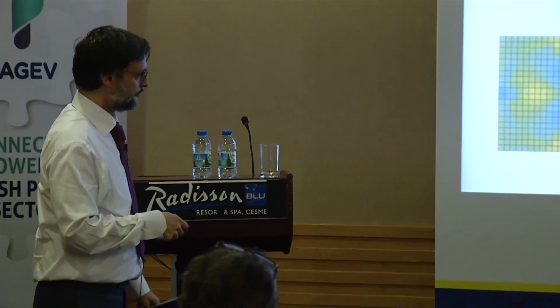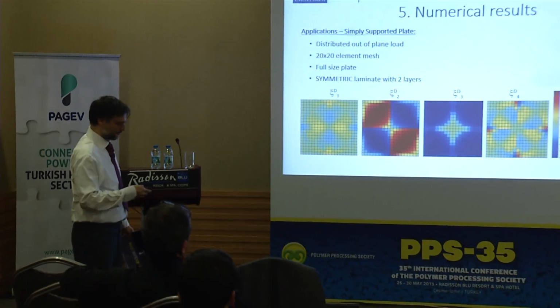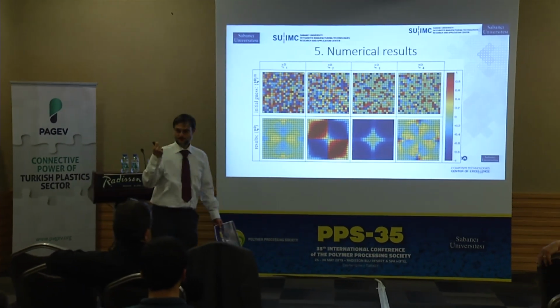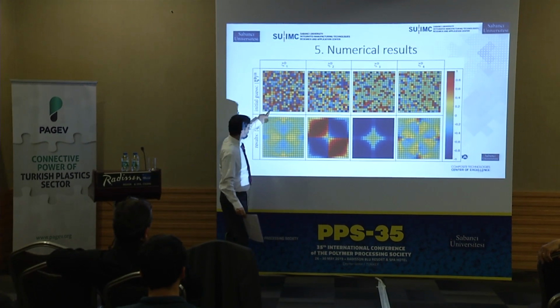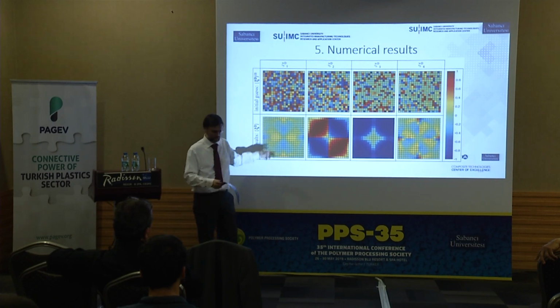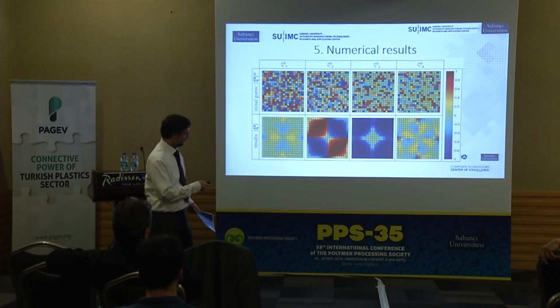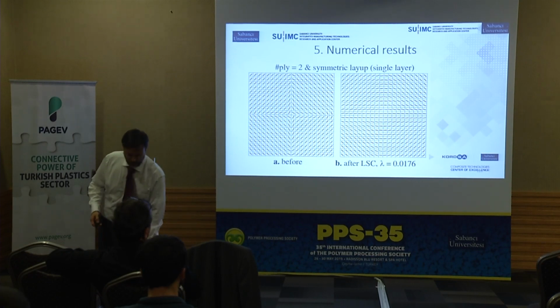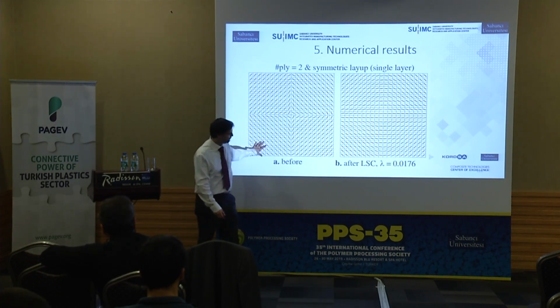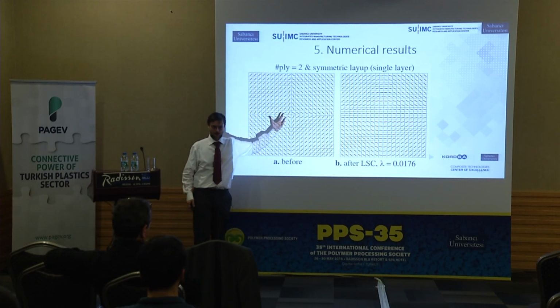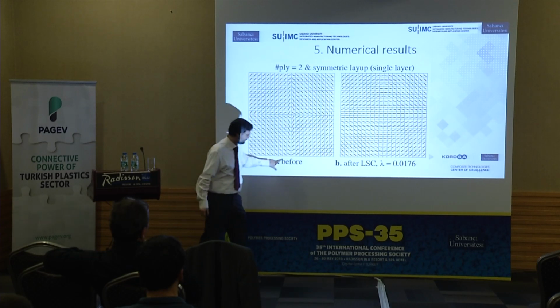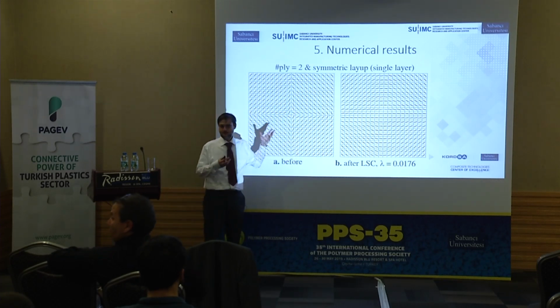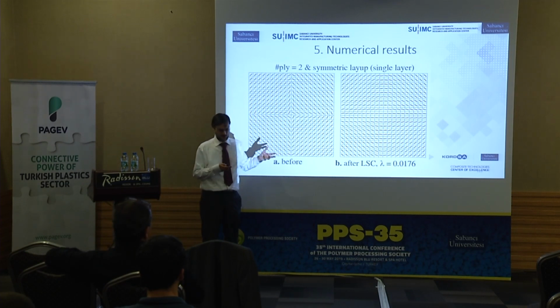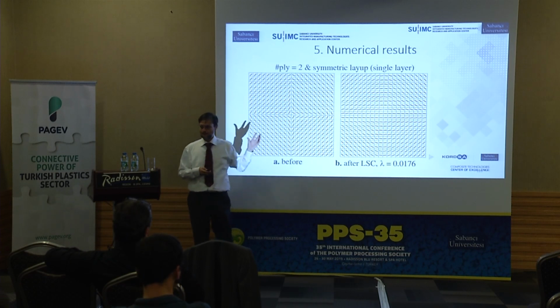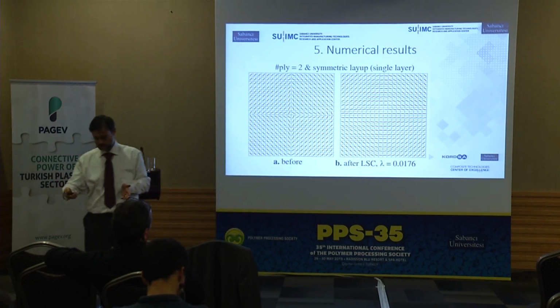Now, this is the optimization result. That is the lamination parameters. We did check the optimization method this way. We assigned each element a random initial guess, and we converged to the same result. That's very important. That shows that your problem is convex, and you can get to the minimum. This is when we convert these lamination parameters to the angles. This is the optimization result for, let's say, a single layer. So when I have a simply supported case, if I can put these fibers in this form, I would have the optimum response. It's like 20% improved with respect to the best constant stiffness solution.